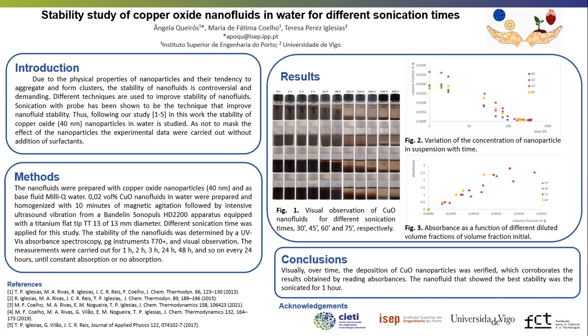The stability of the nanofluids was determined by UV absorbance spectroscopy and visual observation. The measurements were carried out after 1 hour, 2 hours, 3 hours, 24 hours, 48 hours, and so on, every 24 hours until constant absorption or no absorption. The samples were very opaque, so to make it possible to read the absorbance they were diluted 10 times.